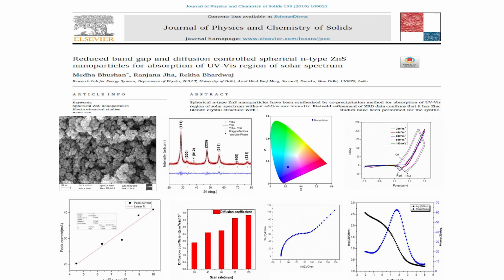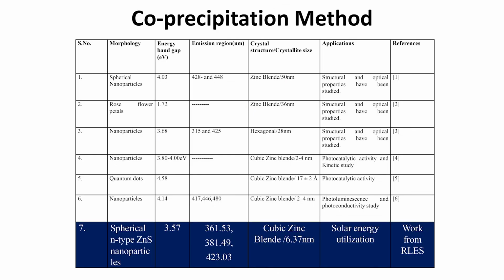For the rose flower petal, zinc blende of crystallite size 36 nanometer. Nanoparticles of hexagonal phase have a crystallite size of 28 nanometers. The other nanoparticles are cubic zinc blende of crystallite size 2 to 4 nanometers, and quantum dots are cubic zinc blende of crystallite size 17 plus or minus 2 angstrom. The utilizations are in study of structural and optical properties, photocatalytic activity and kinetic study, and photoluminescence and photoconductivity study.